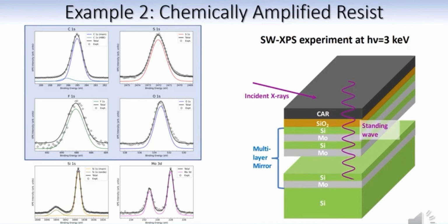One interesting thing to notice is that the carbon 1s was deconvoluted into two spectral components, a high binding energy and a low binding energy one. The low binding energy corresponds to carbon-carbon bonds, and that's expected to dominate the spectrum because this is the backbone of the polymers that are used. The high binding energy corresponds to states where part of the charge from carbon is transferred. So this can be, for example, the case of carbon-oxygen bond groups. As we show on the next slide, the distribution of these two carbon